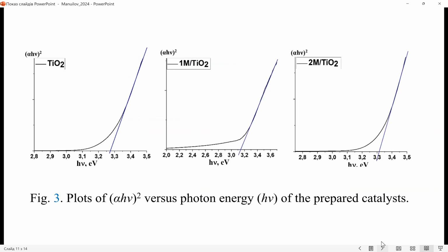Besides, we use UV-vis absorption spectroscopy to measure the band gap of these samples. It was established that the band gap for titanium dioxide is 3.27, for 1M titanium dioxide 3.14, and for 2M titanium dioxide 3.32.